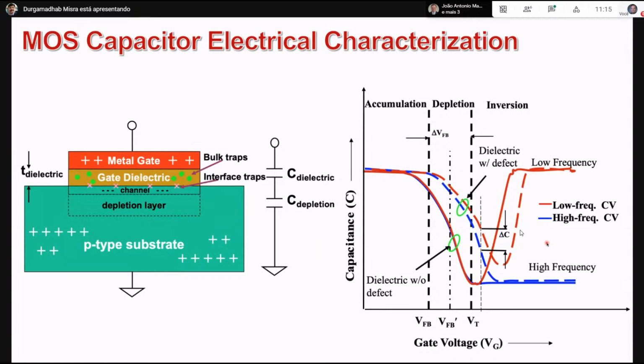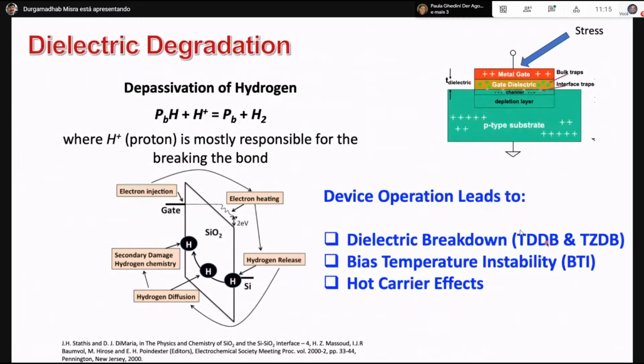The other thing is, when you stress this device, the dielectric also degrades, because when electron injection comes in through the gate towards the silicon, hydrogen can release from those passivated bonds, and then create additional defects inside the dielectric. As we can see here, the hydrogen goes up and creates defects inside the dielectric and also at the interface. So that creates a dielectric breakdown. Also the bias temperature instability, or BTI, which is NBTI for P-channel transistors and PBTI for N-channel transistors.